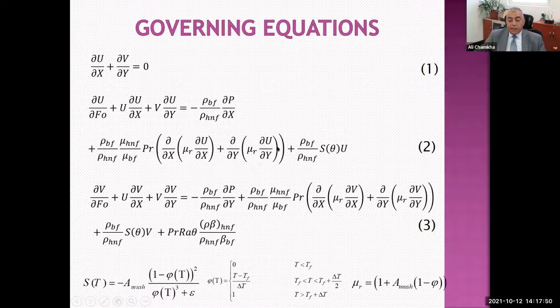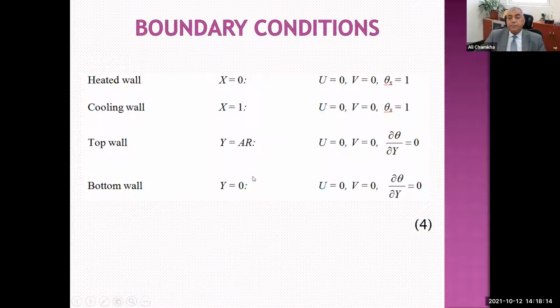In the Kozeny-Carman model, it is assumed that the mushy region is a porous medium, in which, moving from liquid toward the solid part, the porosity and permeability of the medium get very low, and hence the velocity of the fluid tends to zero. And now phi of t here is the liquid volume fraction. These are the typical boundary conditions.